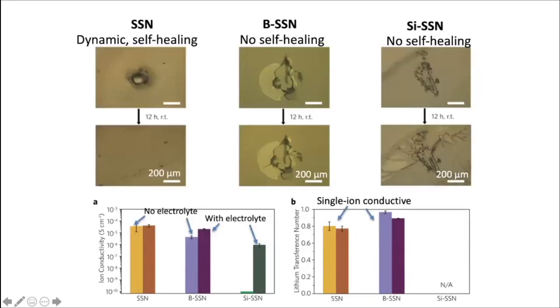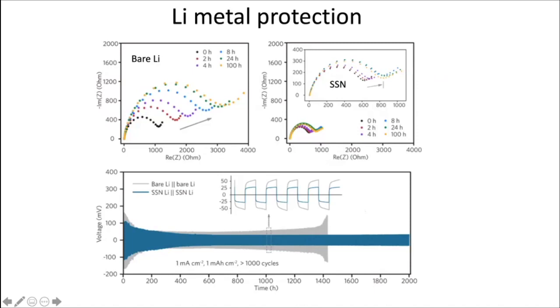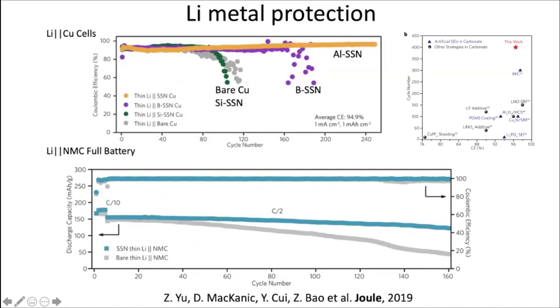So here, I think my time is running out. I'll just go to the final stability of the system. So you can see that with cycling with lithium metal, if we keep the bare lithium metal without any coating in the electrolyte, then we will see that the impedance at the surface will keep increasing. This is because of the formation of the SEI, and it keeps growing because of the reaction, and the impedance keeps increasing. But with our single ion conductive dynamic network, this impedance change is very small over time. And indeed, it gives a stable cycling by using this coating.